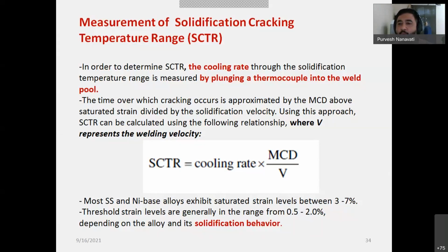You have to calculate the cooling rate. You have seen the test setup, right? You have seen there will be the thermocouple wire plunged near the weld pool. So this will give the liquidus to solidus temperature range, the TL and TS, and the time under which the material is cooled, say 4 degrees Celsius per second, 6 degrees Celsius per second, likewise. So the range divided by the time, when you plot the temperature versus time plot, you get the cooling rate. Multiplied by the maximum crack distance, MCD, and divided by the welding speed or welding velocity V in mm per second. So SCTR is the cooling rate times MCD divided by V, and you will get the solidification cracking temperature range, right?